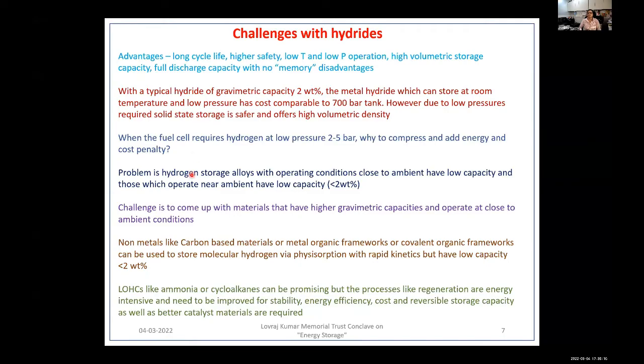Now the problem, with all these advantages, is that the metal hydrides which operate close to the ambient conditions have a lower capacity, while those materials which operate at a higher temperature and pressure have a higher capacity. So what is required is to come up with materials which have a higher gravimetric capacity and at the same time operate close to ambient conditions of temperature and pressure.